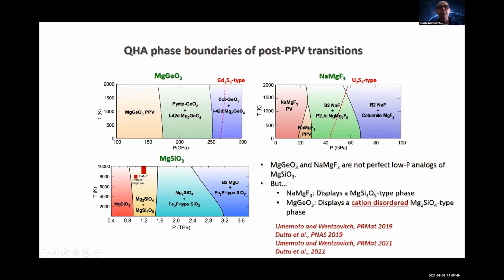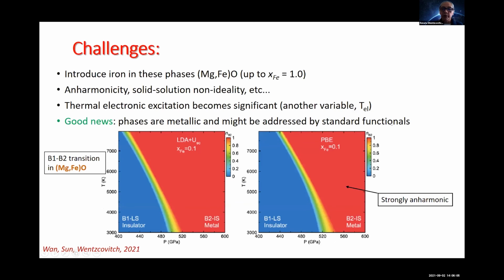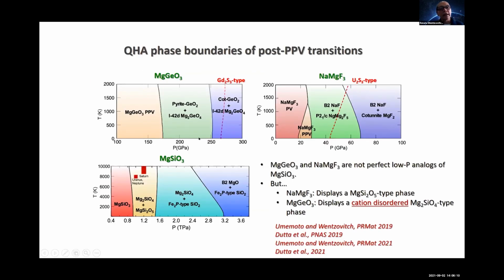Interestingly, recombination or decomposition transitions are hard to happen. I mean, high hysteresis, and some metastable polymorphic transitions can be observed as well. So here are the latest predictions and measurements on the magnesium germanate phase, the Mg2SiO4-type phase, which turns out to be disordered. There is cation disorder. The similarity of sites and bond lengths, MgO and SiO bond lengths, produces a cation-disordered phase. This is very interesting. That is going to complicate our work a lot in making predictions for exoplanet super-Earth relevant phases. But here we have cation disorder in these phases.